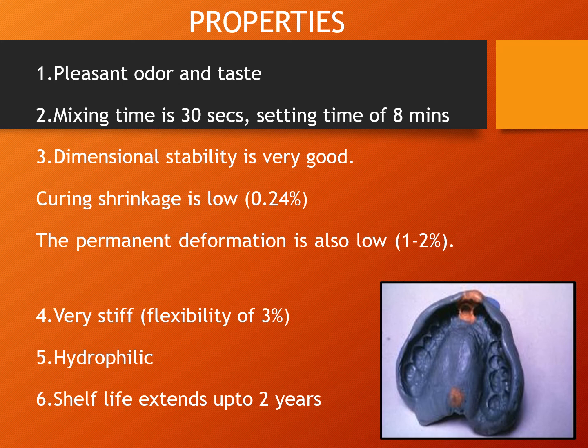And it is a hydrophilic material, so there is no problem of moisture control, and the shelf life extends up to 2 years, and polyether is stable only if stored dry because it will absorb moisture and undergo significant dimensional changes. Also, some cases are there of allergic hypersensitivity in polyether elastomer.